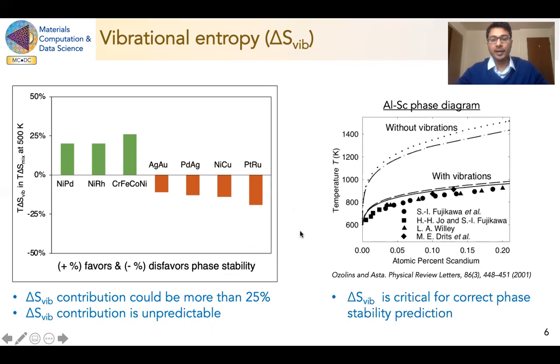Now, the importance of vibration entropy has been discussed and shown in the literature also. Just for an example, this is from the aluminium scandium phase diagram. And the vertical axis is showing the solubility temperatures as a function of atomic percent scandium. The solid data points show the experimental values, and the dotted, solid, and dashed lines are from the DFT calculations. And you can clearly see that with the inclusion of vibration entropy, correct solubility temperatures are predicted, which shows that the vibration entropy is very important for the correct predictions of phase stability and solubility temperatures.